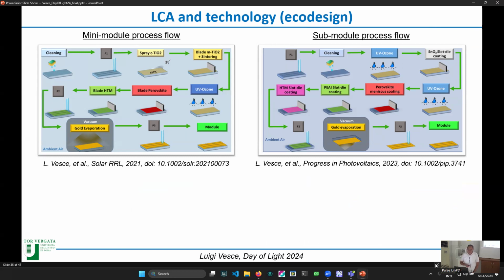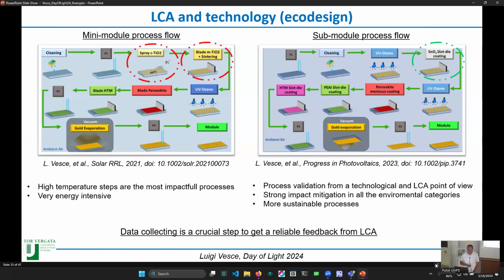So this means that when you are designing a process, you start to think about the impact that this process can have on the environment. Here is the comparison of the two processes, so mini module and sub module. And the life cycle assessment testifies that the choices that we made are good also from a technology point of view. For example, in the mini module, we still use the spray coating at high temperature, the blade coating, and the sintering at high temperature.